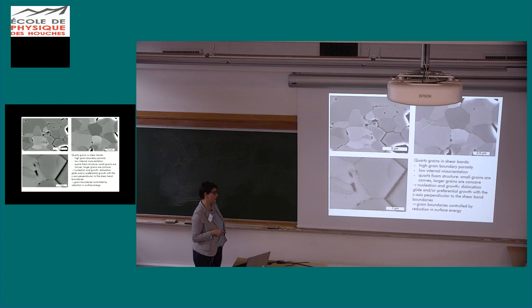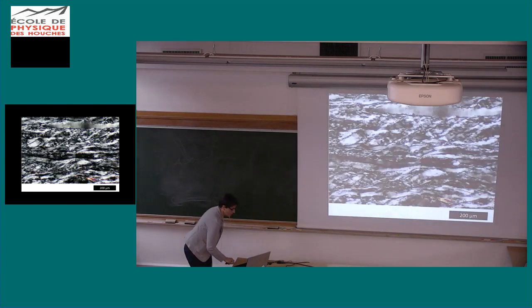So here we have some evidence that after dislocation creep, even the grain boundaries were controlled by the reduction in surface energy to make this a nice foam structure. So that would point to nearly, almost static conditions at some point in specific areas.